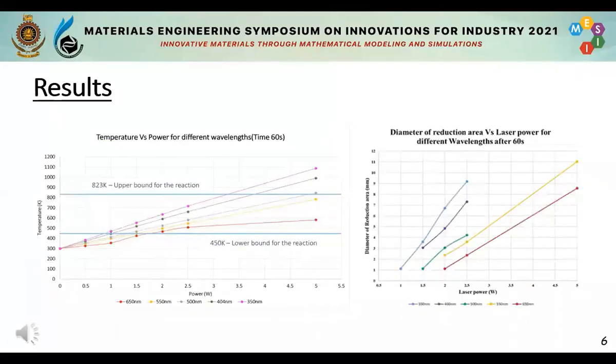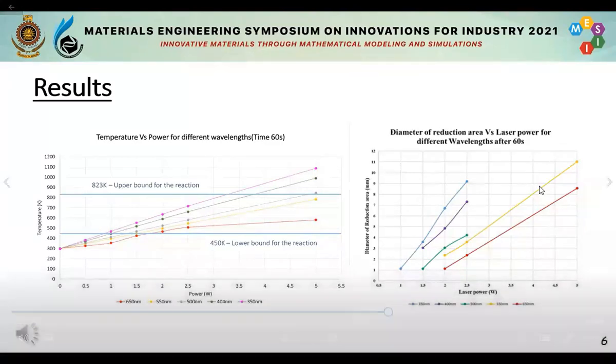We selected several wavelengths and powers for our project. Wavelengths were selected in the range of 350 to 650 nanometers. Powers were selected in the range of 0.5 to 5 watts. Then we plotted temperature versus power for different wavelengths in a time period of 60 seconds in order to find a suitable laser combination. Here we used our lower bound for the reaction as 450 Kelvin and the upper bound for the reaction as 823 Kelvin. Selected laser combinations were used for reduction, and temperature distributions along the surface of the graphene oxide film were separately plotted. Then a resultant graph was generated in order to find the diameter of the reduction area according to the laser power.